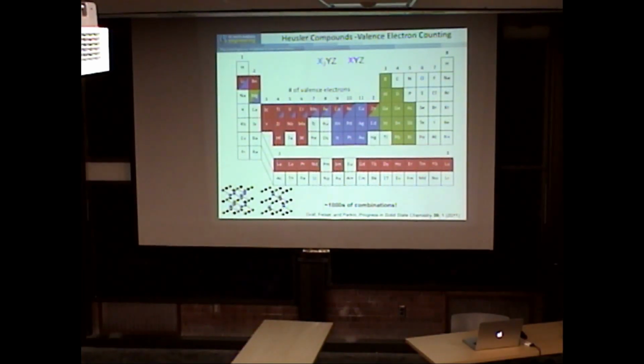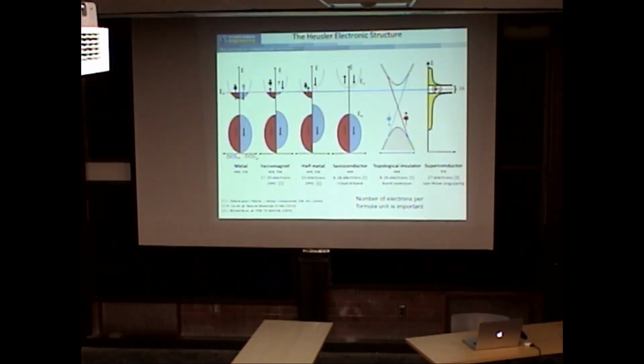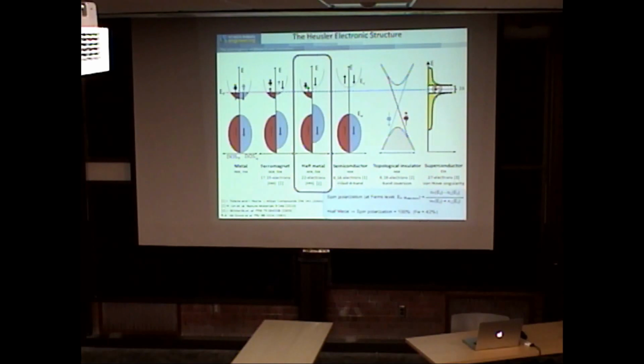I should point out another thing, because I'm going to come back to it. Think of the number of valence electrons we have across all these groups. What's going to be important is that the number of valence electrons per formula unit has a big effect on the electronic properties. So these materials can be metals, with equal Fermi levels, where you've got up and down spins. They can be magnetic, if you've got an imbalance of spins. They can be half metals, where one spin is metallic and the other spin is a semiconductor. The Fermi level is in the gap, and this should in principle give you 100% spin polarization at the Fermi level. This is something we're really interested in for spintronics, because now I can have just one spin that I'm playing with.